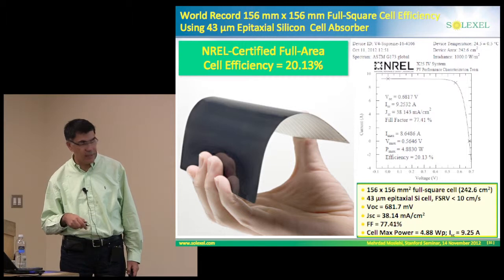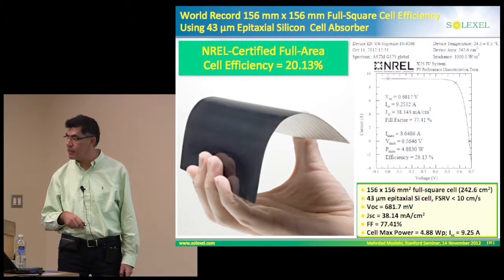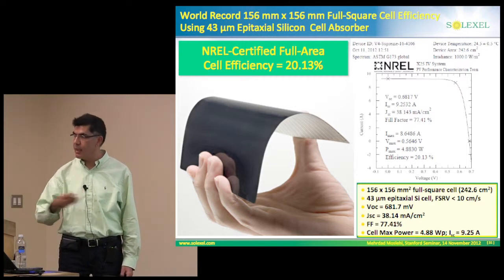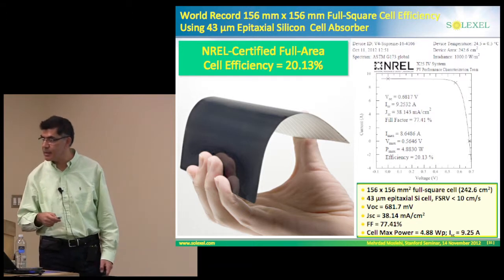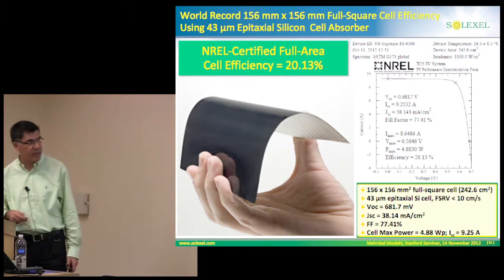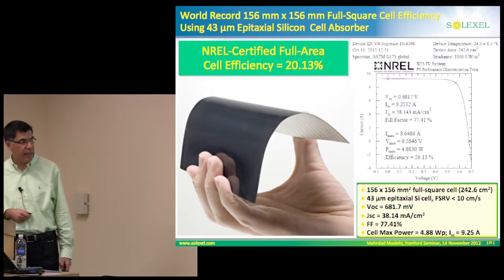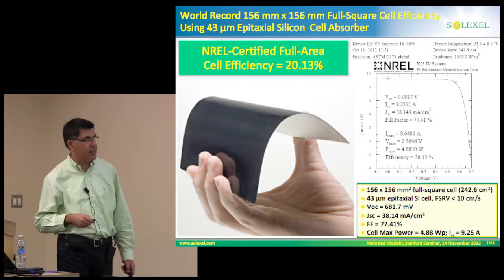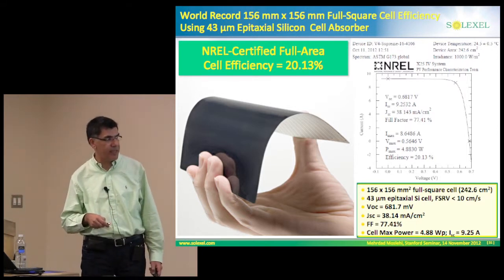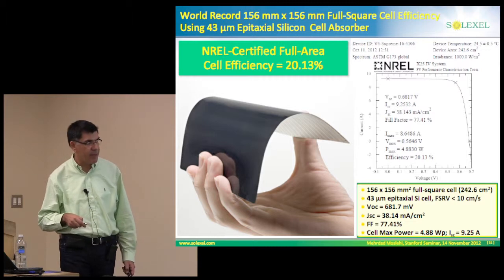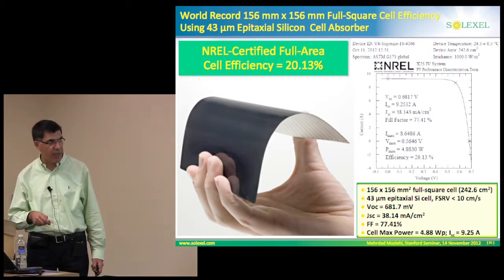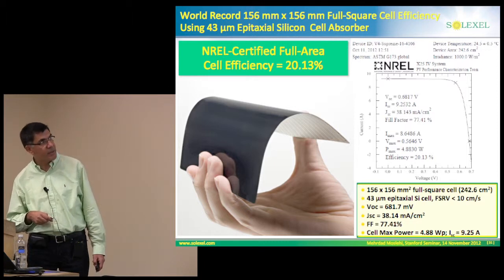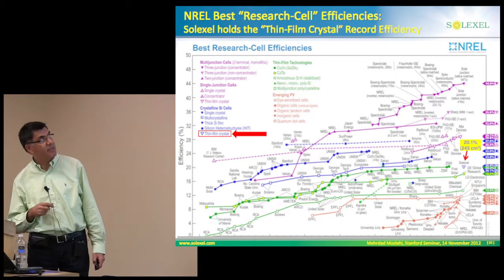You know, the VOC is over 680 millivolts. This is actually larger than any front contact cell you see out there. We expect this to go in the near future over 700 millivolts. JSC over 38 and fill factor over 77%. So the cell power is 4.9 watts and short circuit current 9.25. So in fact, this landed us on this NREL's